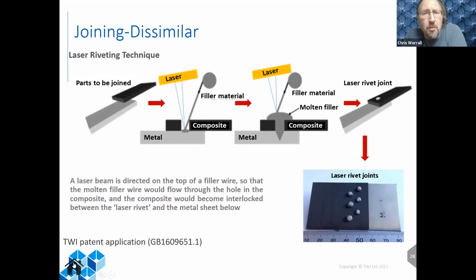You can think of it almost like an additive manufacturing. So we put a composite and a metal together, and then using laser, we melt a filler material to produce a laser melted rivet inside the joint. The advantage is that the rivet is built on top of the metal and then overflows around the top of the composite without having to put a hole through both components. So we only get the witness marks of the rivet on the composite side. So the other side of the metal is completely free, aerodynamically clean, and visually beautiful.